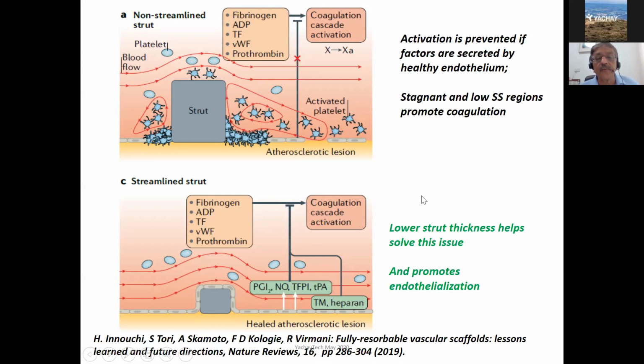So this is now well accepted and has led to many people working on lowered strut thicknesses for both the metal stents as well as for biodegradable metal stents and biodegradable polymer stents. So you can also make biodegradable stents out of magnesium and iron, and many people are working on reducing the thickness of these magnesium and iron stents. The Amaranth second and third generation stents are much lower in thickness. In fact, the latest version is about 80 microns. Okay, and this is a very difficult thing to achieve with polymers.